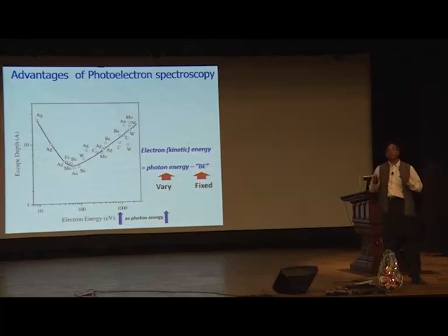So basically, the photoelectron signal is the one which does not scatter inelastically. So it's very important to know what is the probability that this electron will come out of the material without suffering an inelastic process, and that we characterize by a typical length scale, which is the average length or distance that an electron can travel inside a given material without being scattered inelastically.